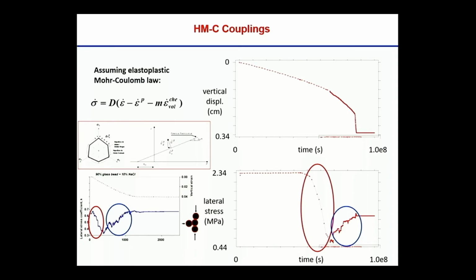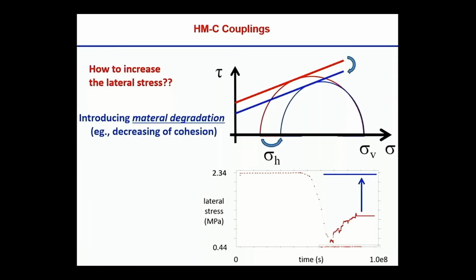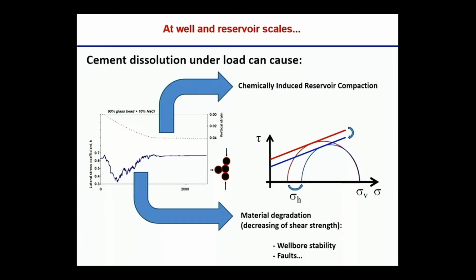So we now introduce a material degradation. If you have a constant vertical stress and we introduce a material degradation, we have this decrease of the stress envelope, and the only way for the horizontal stress is to increase. So we are able to increase this. It's a mechanism that we are introducing to control this. There are more sophisticated models we are working with.